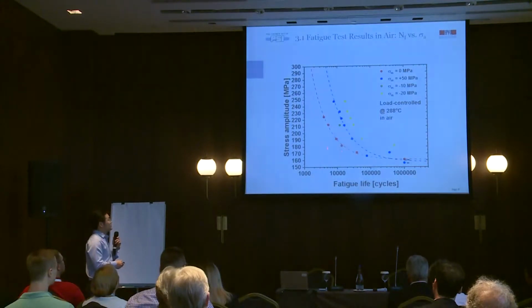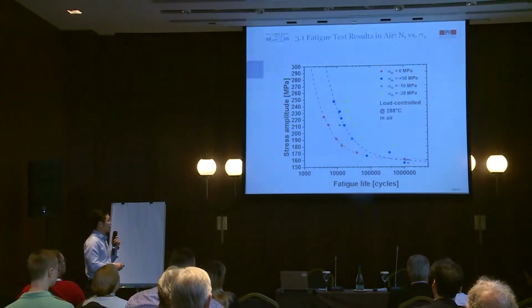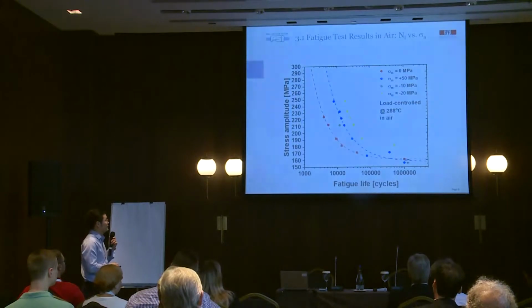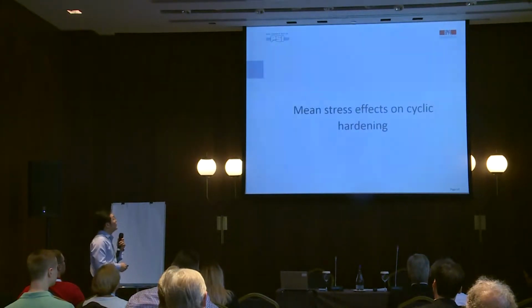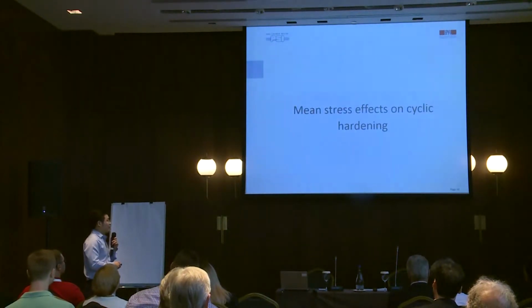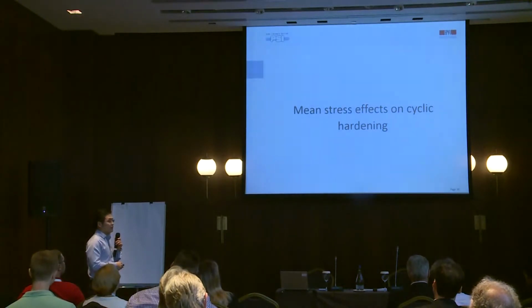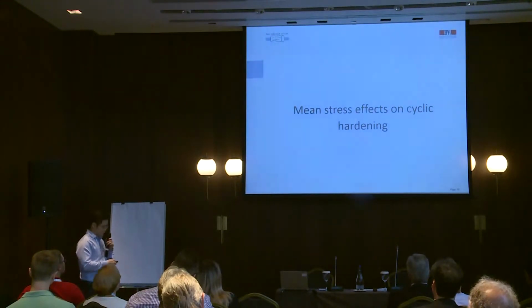And this is the test in the air condition. We found that it has a similar mean stress effect in the air condition, except the 50 MPa mean stress in the high cycle fatigue region, which still needs to be confirmed by further tests. And what is the mechanism behind the mean stress effect? Maybe the direct answer is the cyclic hardening.